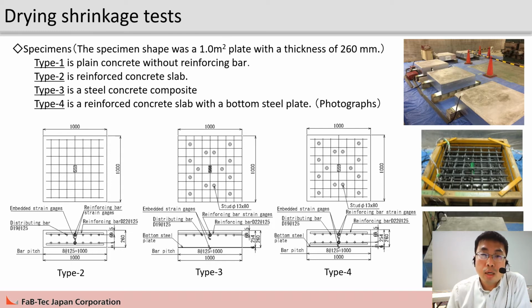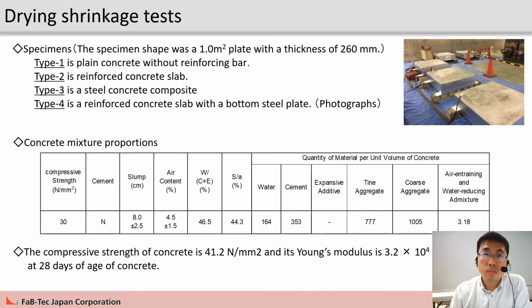Aluminum tape was attached to the side surface to ensure that the upper and lower surfaces remained dry. A Teflon plate was laid on the support plate to reduce the influence of friction. The concrete mixture proportions and material properties are as shown.